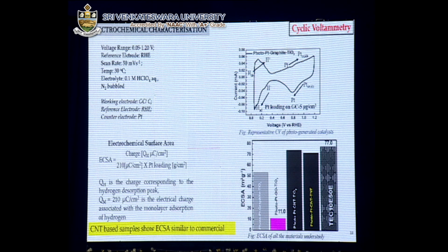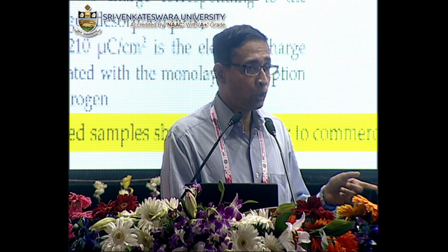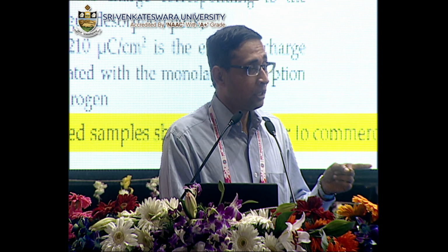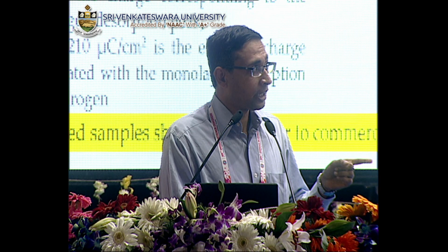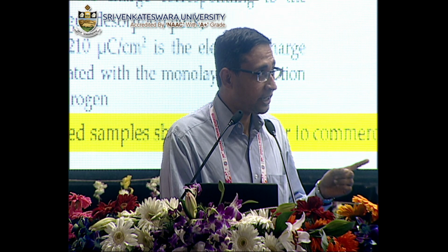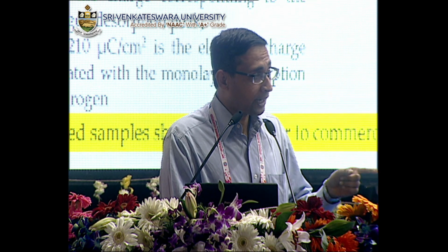These fingerprint regions are depicted on the top right hand corner. If you see this, there is a huge peak on the left hand side of the voltammogram. On the left hand side there's a peak for the hydrogen evolution region or the hydrogen desorption region, which is very important for us to know that the platinum is studded over the carbon. As we go up to the right hand side, we see the oxygen evolution reaction taking place, and as we come down there is the oxygen reduction reaction taking place, at the bottom right hand side.